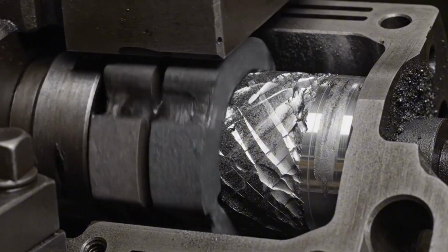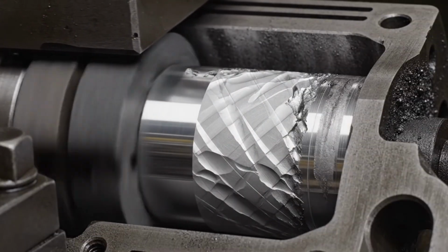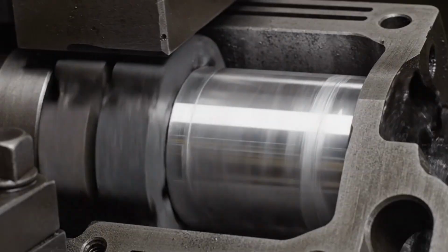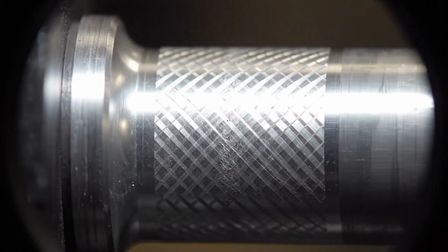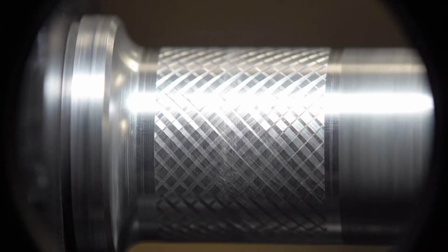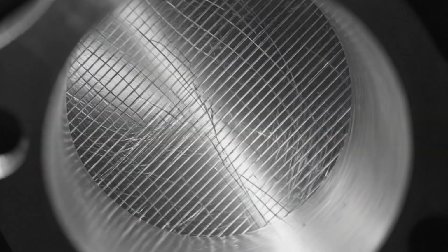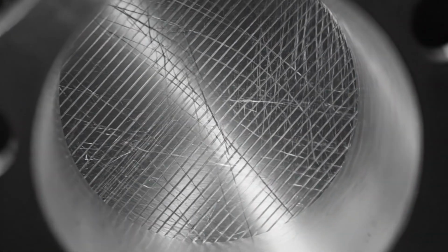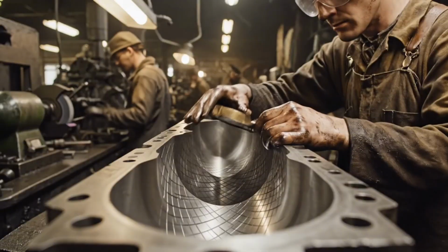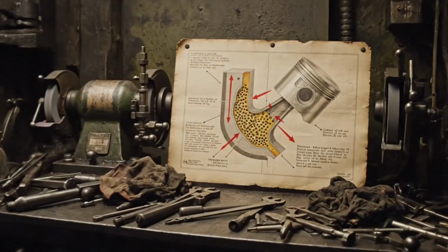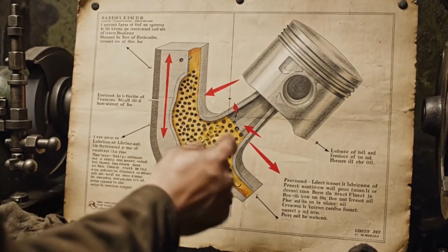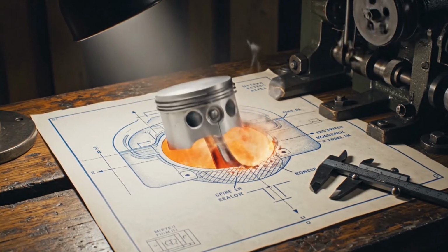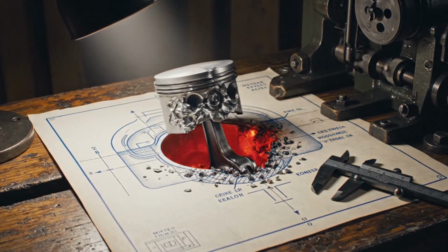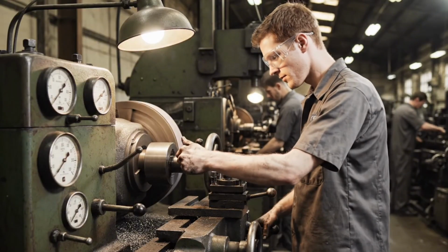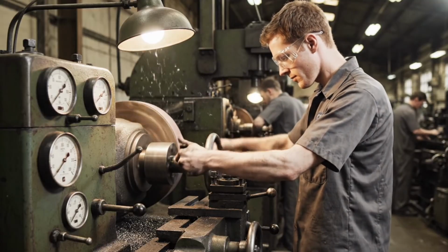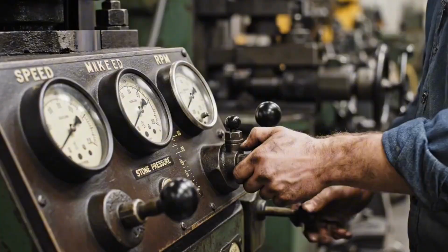After boring, each cylinder chamber was finished on a honing machine. Honing used abrasive stones mounted on a rotating and reciprocating mandrel to smooth the bore surface to a finish that was almost like polished glass. But the stones did not leave the bore perfectly smooth. They left a crosshatch pattern, a deliberate surface texture made up of fine diagonal lines running in opposite directions. This crosshatch served a critical purpose. It trapped small pockets of lubricating oil on the cylinder wall and prevented the piston from making direct metal-to-metal contact with the bore. Too much contact and the friction would generate heat, consume oil, and wear through the bore surface. The crosshatch was the invisible mechanism that kept the engine alive cycle after cycle after cycle.